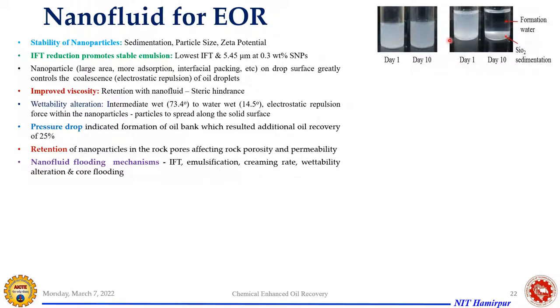We have taken the nanoparticles, we have studied the stabilization, and as I've said, in formation water the nanoparticles are agglomerating, so the electrostatic interaction forces are pretty high, that's why they are getting agglomerated and settled at the bottom. And you can see, these are going through the destabilization process. So in this case, the nanoparticles are not stable, but in this case, when we have surfactant and polymer,